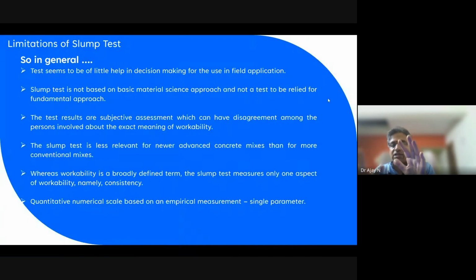So in general, we can say the slump test is not much relevant for today's advanced concrete like SCC, GPC, FRC, and lightweight aggregate concrete. The main concern is that this is not a material science approach. It is a subjective matter, and we take quantitative measurement scales like 10 mm, 12 mm, where clearly we are measuring a distance. It is based on single point parameters. We are judging the concrete using one parameter, like a distance.